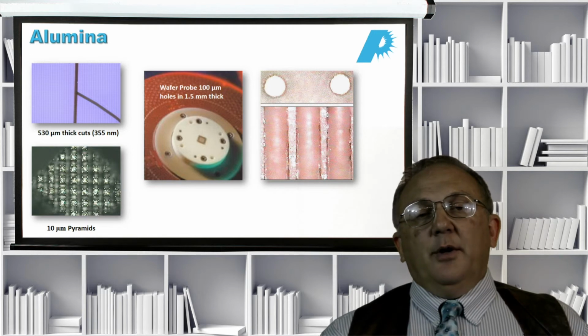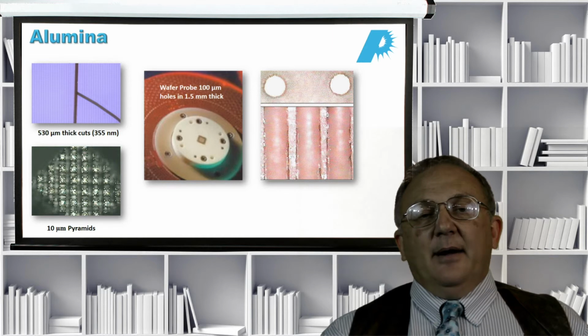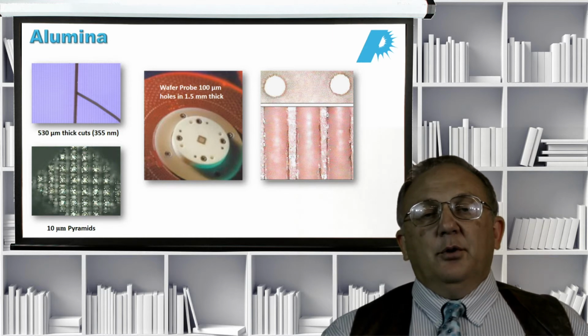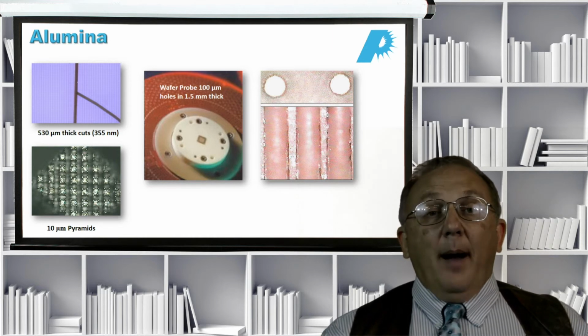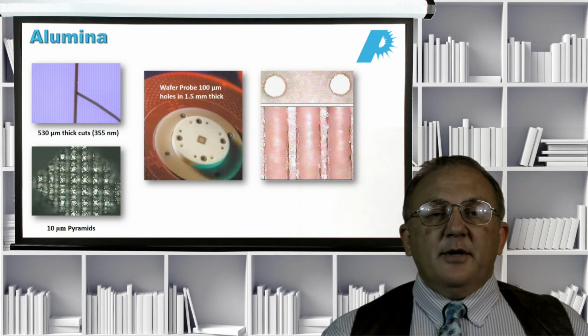And this is very important when you talk about applications such as probe testing, because wires are stuck down in those holes. And if the holes are too large, the wires will wobble around and you won't get a good contact. And if they're too small, well, you just can't get the wire in. So the holes have to be very precisely manufactured with tight tolerances.